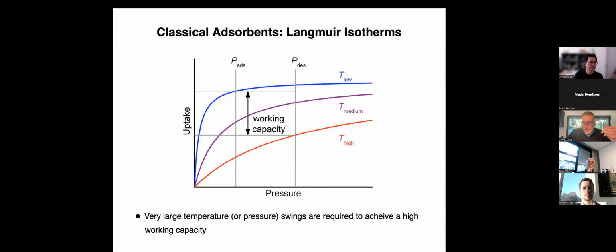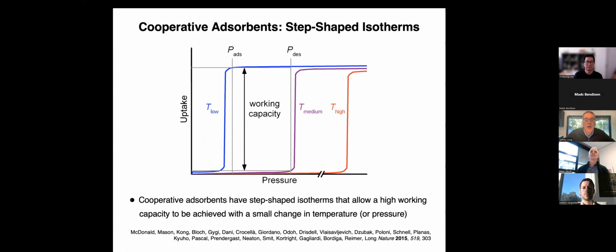And if you were just to try and reimagine what these isotherms should look like for a very efficient CO2 separation, then you probably wouldn't come up with Langmuir isotherms. Instead, you might come up with something that looks like a step. And so step-shaped adsorption isotherms can arise for cooperative adsorption processes. And what it means is that in such a case, you go to a sudden condition where you go from no loading of CO2 to hitting a temperature and pressure where all of a sudden it's spontaneous for CO2 to load into the material. And at that point, you can go from no loading to filling up your material with carbon dioxide. So there's a switch-like behavior.